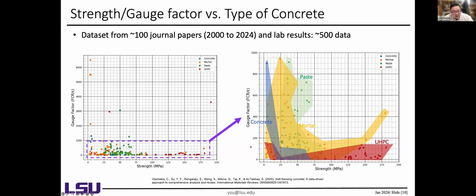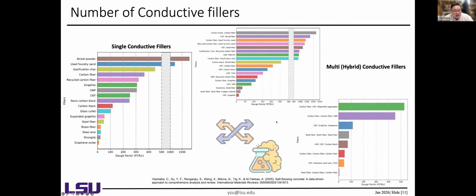So then we conducted a really comprehensive literature review of around 100 journal papers from 2000 to 2024 and collected some data to plot the gauge factor versus the strength. And we classified them into concrete, pastes, mortar, and some UHPC. We can see that some papers present really high gauge factors, especially for concrete, mortar, and pastes. And in terms of the conductive filler, we also noticed that people not only use a single type of conductive filler, some people use a hybrid of different types of conductive filler together, and some of them get extremely high gauge factors. So we are trying to figure out what type of conductive filler we're going to use.